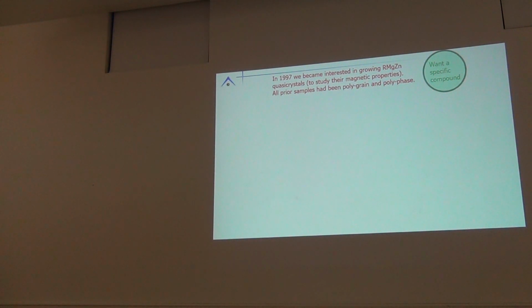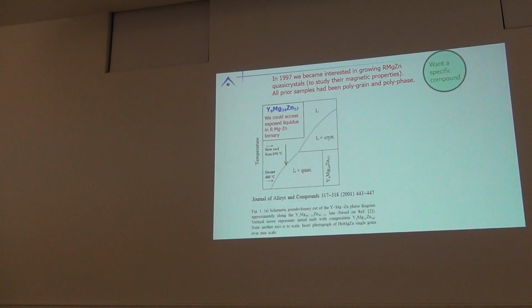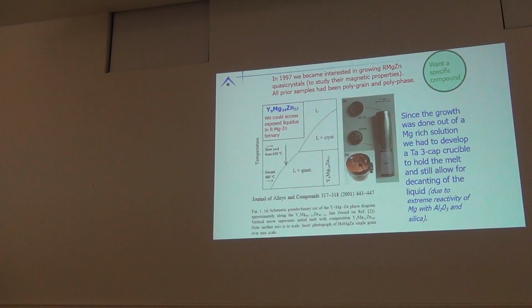Okay? The problem was the samples were all polycrystalline and actually multi-phase. We were able to figure out what the phase diagram looked like. This is the compositional phase diagram. We could grow this out of excess magnesium and zinc. There was an exposed liquidus line that let us grow the quasicrystal. But since we're growing out of excess magnesium, this eats away at alumina, at silica.